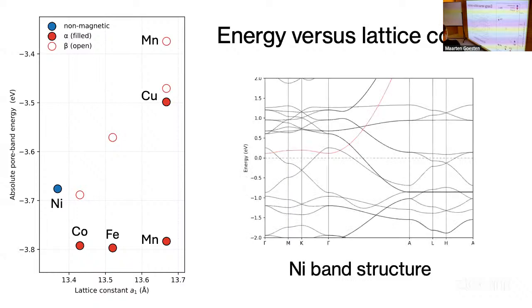So this actually doesn't tell you how close it is to the Fermi level, because if you have nickel, a chemist will tell you that nickel has more electrons than cobalt. Nickel has 10 electrons. So actually, in this case, nickel, we find that the pore band lies the closest to the Fermi level. It's very close to becoming occupied.